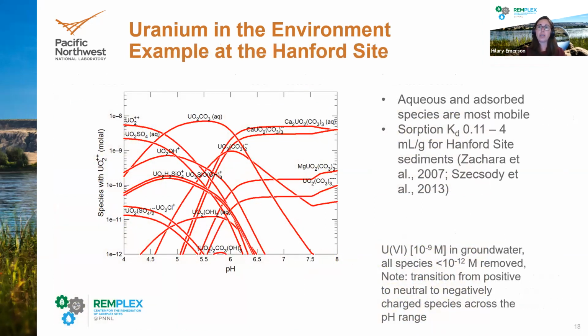And so before we transition over to some of the characterization, I wanted to end with an aqueous speciation diagram that shows all of the species that we might see. So we've seen the simplified Pourbaix diagrams, but this shows that in the neutral and alkaline pH range, we primarily see these uranyl carbonates and calcium and magnesium uranyl carbonate species, whereas as we move into the acidic range, we primarily see the uranyl cation and also uranyl sulfate species. And these are important to understand because they'll directly correlate with the potential for sorption and precipitation in these environments.